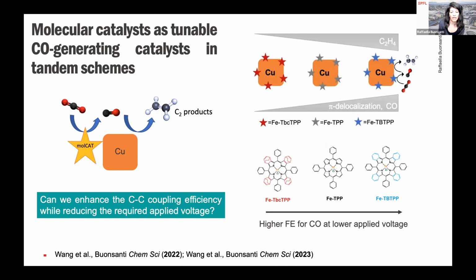not only when coupling this copper with another metallic domain, in the case I mentioned was silver, but also, for example, if we start coupling copper with a molecular catalyst. So actually, we can also start picking molecular catalysts, which are CO producers, instead of metals. And the advantage of molecular catalysts is that we can change their production rate for CO and the voltage at which the CO is generated, depending on the ligands that we have around the active center.